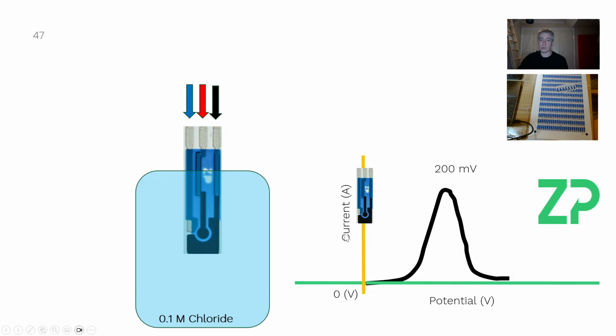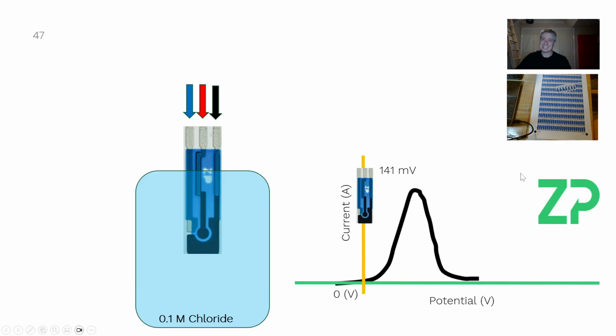So that person wouldn't record the oxidation peak potential at 200 millivolts. They would say, no, it was actually 141 millivolts. It's because you're both using silver chloride, but you're in different chloride concentrations. With a pseudo reference electrode, you're sensitive to the chloride concentration. Now, this doesn't arise very often as a problem because people are so often using a known chloride concentration in their experiments, and they always use the same chloride concentration, so they always get repeatability. But if you just change that chloride concentration one day, then all your potentials could shift accordingly. So just know about that.